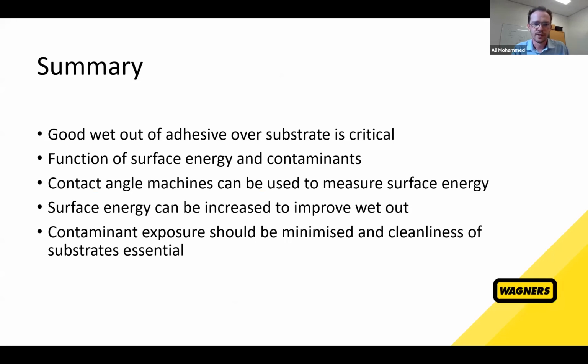So just to summarize, good wet out of the adhesive between two substrates for a bond is critical. And the wet out is a function of both the surface energies of the substrates and the presence of any contaminants. You can use the surface energy to evaluate how your surface is going in terms of being ready for bonding. There are machines available that can measure this, and you can use a variety of different techniques and processes to increase the surface energy of your substrates for that bond. And then obviously contaminants are a no-no, and you should be looking at ways to reduce exposure to those contaminants. As I said, some industries have banned silicone and that sort of thing, so quite serious. But you should be looking at whether you can remove any sort of contamination process from your bonding area in your factory, if that's your setup.